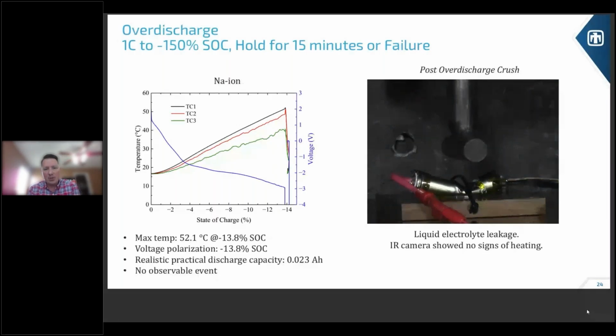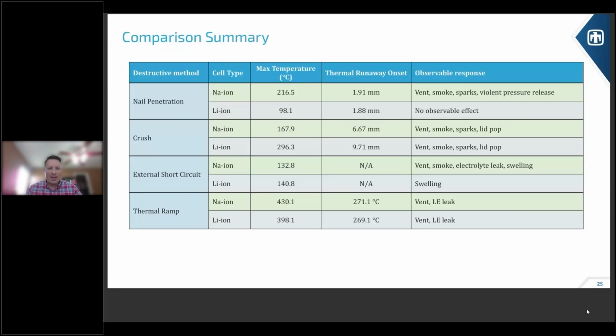We also did a post-over discharge crush on this one just to make sure it was safe. And in this case, it was safe. We had an infrared camera on it, and we saw no signs of heating, just some liquid electrolyte leaking out because we're mechanically crushing it. Next. So unfortunately, I have a lot of slide transitions here, so I think I'll just talk through it as is, and then you can go to the end after.